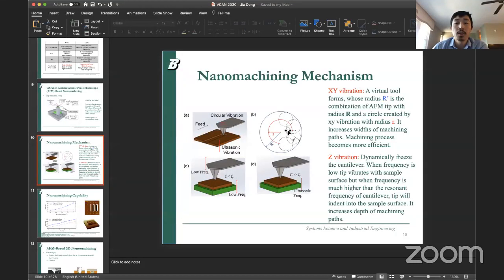As you can see, the resolution depends on two things. One is the tip vibration, and another is the tip size. The vibration amplitude can be tuned from 0 all the way to about a few hundred nanometers. So it's a trade-off between the resolution and your nanomachining efficiency. If you want a high resolution, you lower the XY in-plane vibration. That means the virtual tool size is the tip size plus the vibration amplitude. If you want high efficiency, if you want to create a very wide trench with one machining path, you can increase the vibration amplitude. So the ultimate resolution is the AFM tip size plus a little bit of XY vibration, if you want to say it.